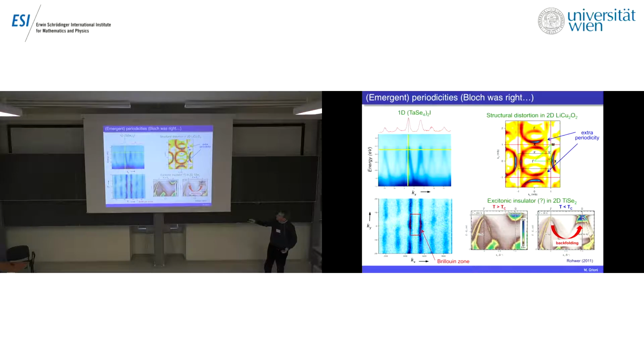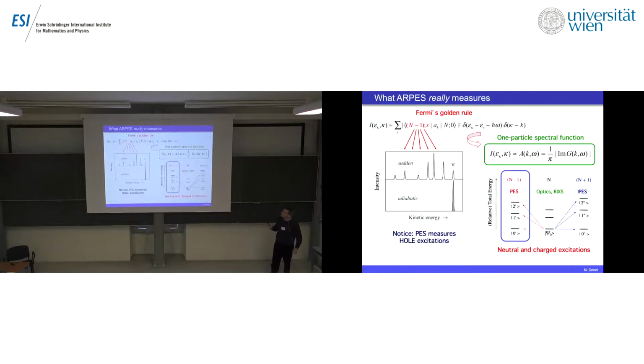And we can measure also emergent periodicity, like in this two-dimensional material, titanium diselenide, which has a charge density wave transition. At the charge density wave transition, there is a new periodicity, and you see that all of a sudden, this band is reproduced at a different place. It's backfolded. So ARPES shows band, shows periodicity. But actually, this is not what we measure.